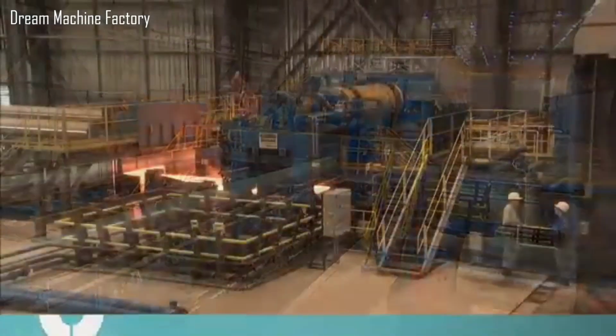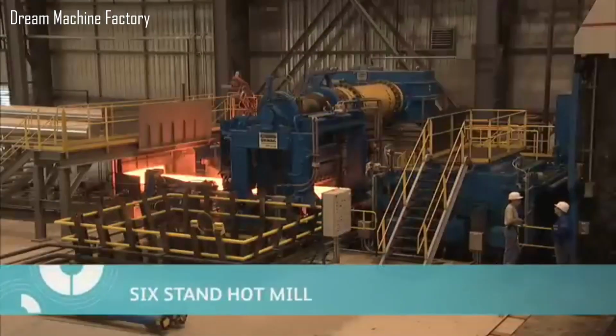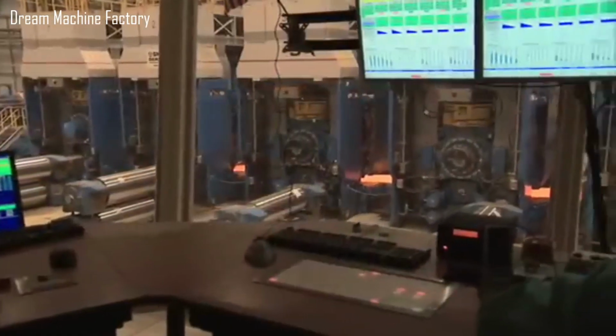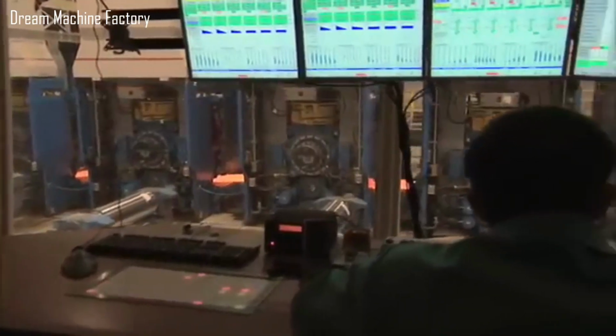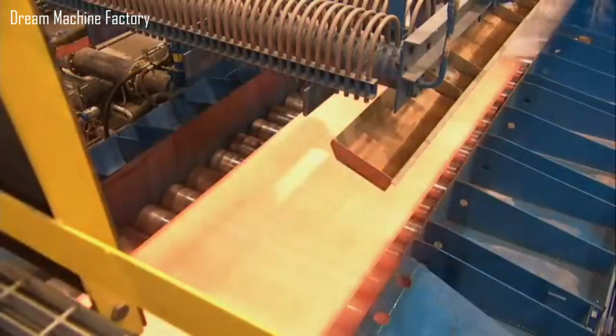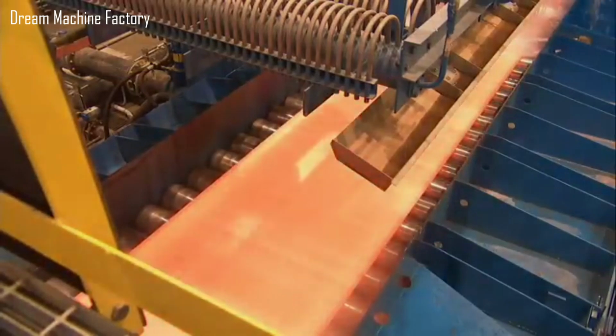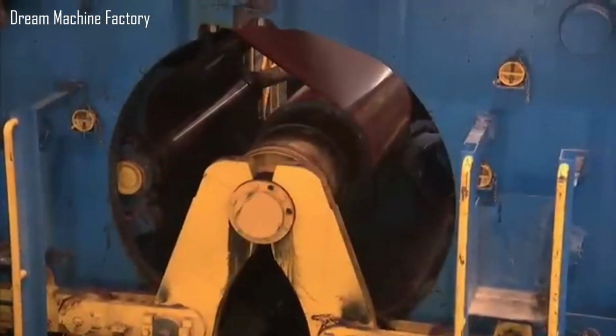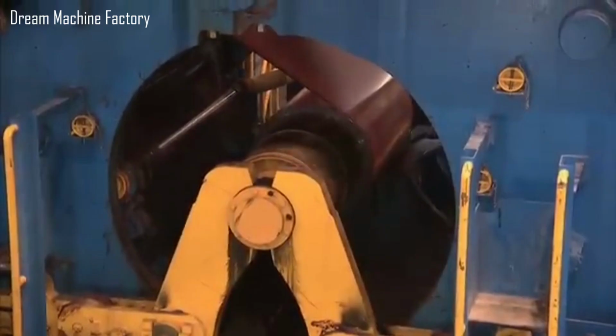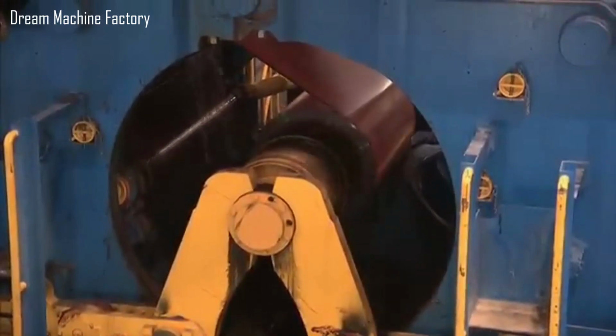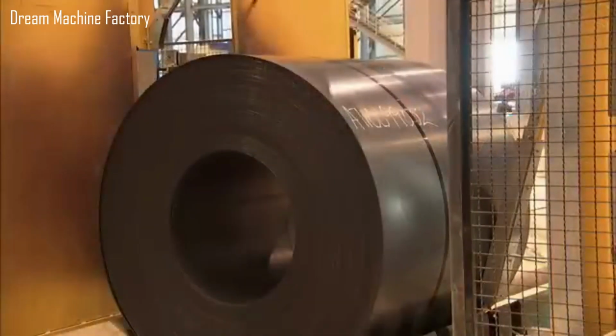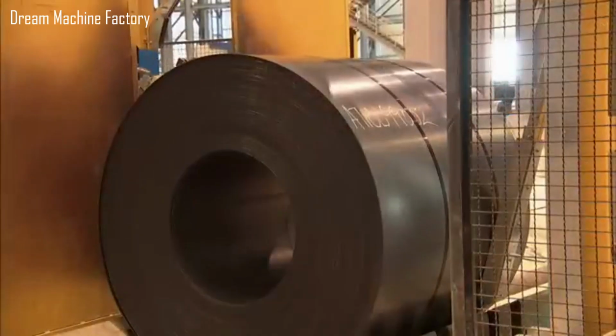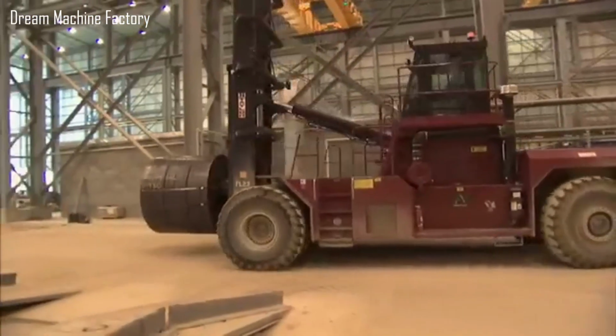The 6-stand hot mill reduces thick steel slabs into thin strips with precise dimensions and surface quality. As the reheated slab enters, it passes through 6 powerful rolling stands, each progressively reducing thickness while controlling shape and uniformity. Starting at 2.5 inches, slabs can be reduced to as thin as 0.054 inches. The process ensures strength, flexibility, and versatility, producing coils suited for automotive, construction, pipe, and appliance applications.